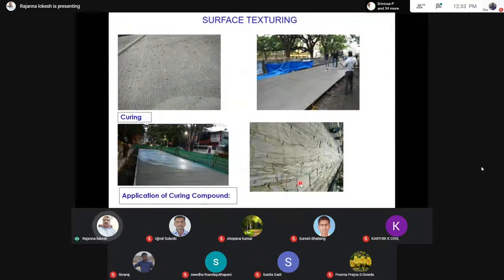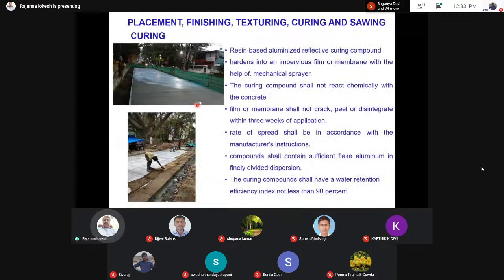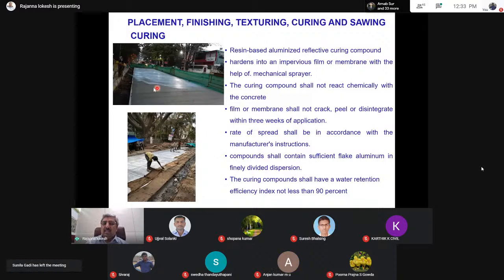So you can see the curing being done using curing compound. The curing compound can be resin-based or aluminum-based. It gets hardened and forms a thin film on top of the concrete surface, so that there is no evaporation loss from the concrete. It is all the more important to understand and utilize curing compounds which will not react with the concrete.